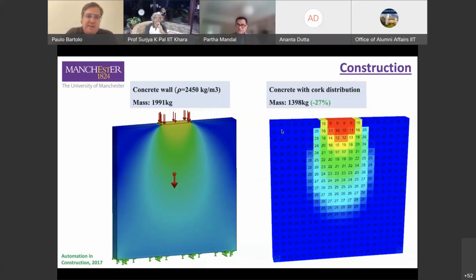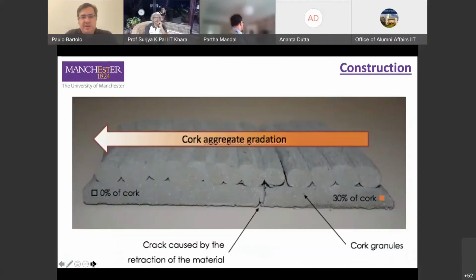30% was a limitation, mainly because we need to have more expensive pumps. The viscosity is a problem here, but we can go to high levels of cork. So to print this kind of structure, it was necessary to create a new printing head, a novel mixing system to mix concrete and cork, and to change the composition in real time during the printing process.